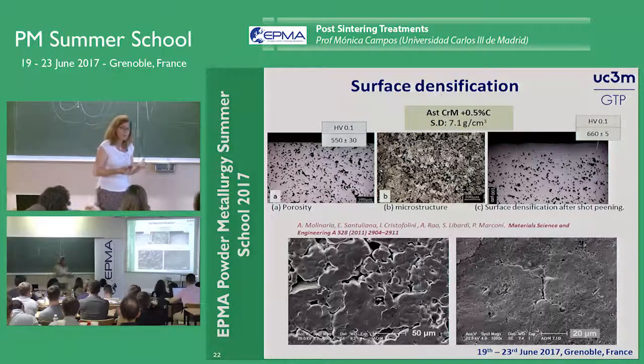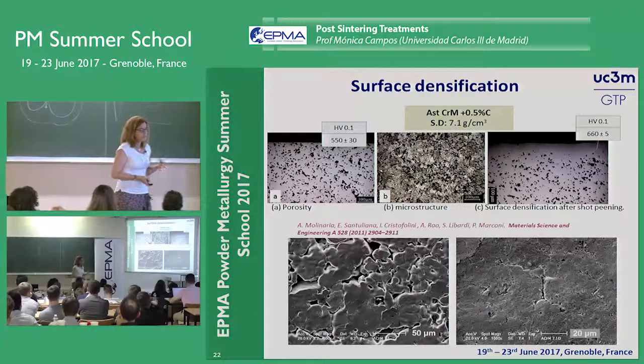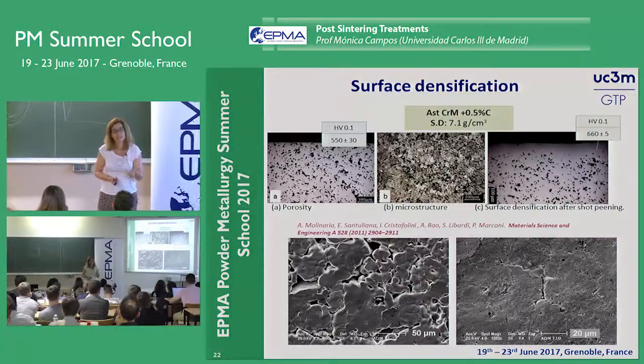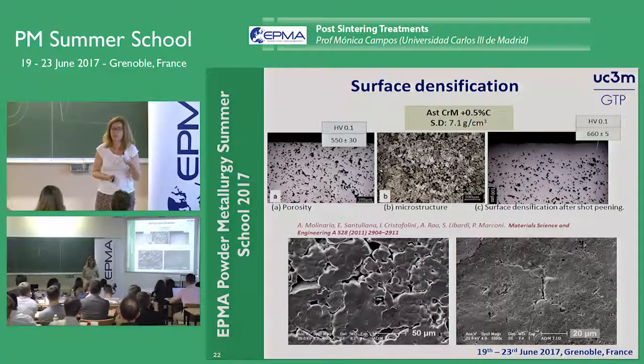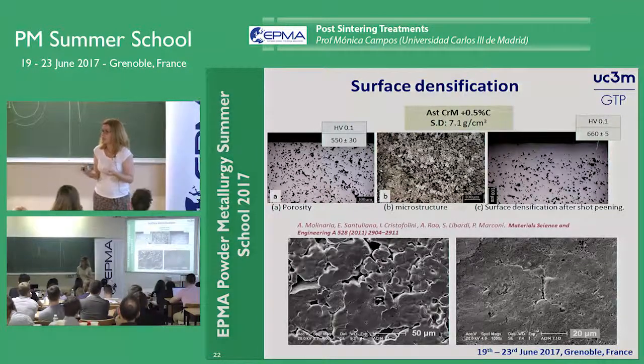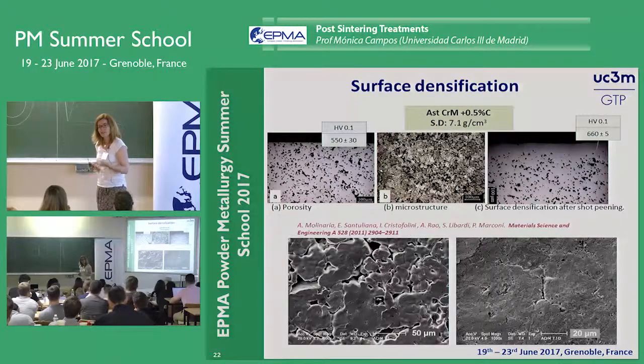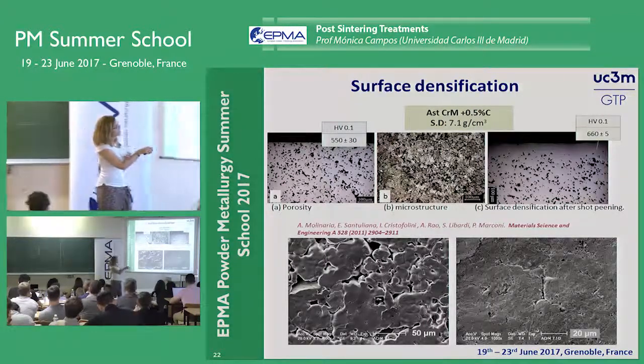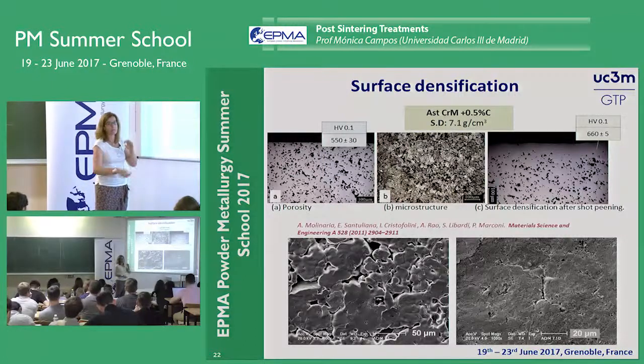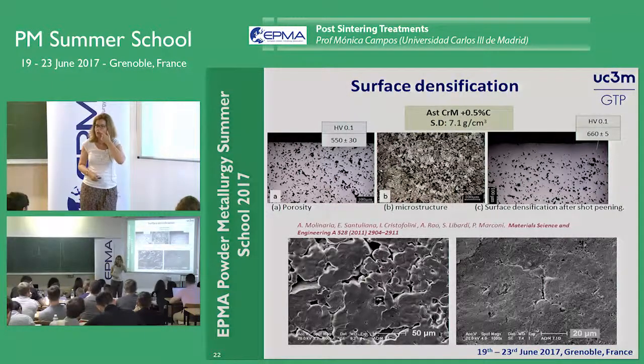And also, after this treatment, the material is more sensitive, more reactive to chemical treatment, surface treatment like case hardening or nitriding. Because in this part we close the porosity, we can better control the diffusion that is happening in this area.